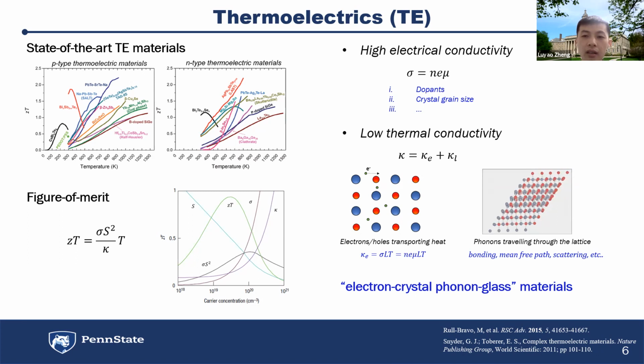As I mentioned, we need a high electric conductivity and also low thermal conductivity, as the ZT equation shown here. So we relate to these two parameters. We want a higher electric conductivity. Probably we can use some dopants to optimize the materials. And also we can try to use some method to enlarge the crystal size to give us higher mobility of the materials. And on the other hand, for the thermal conductivity, usually it can be divided into two parts.